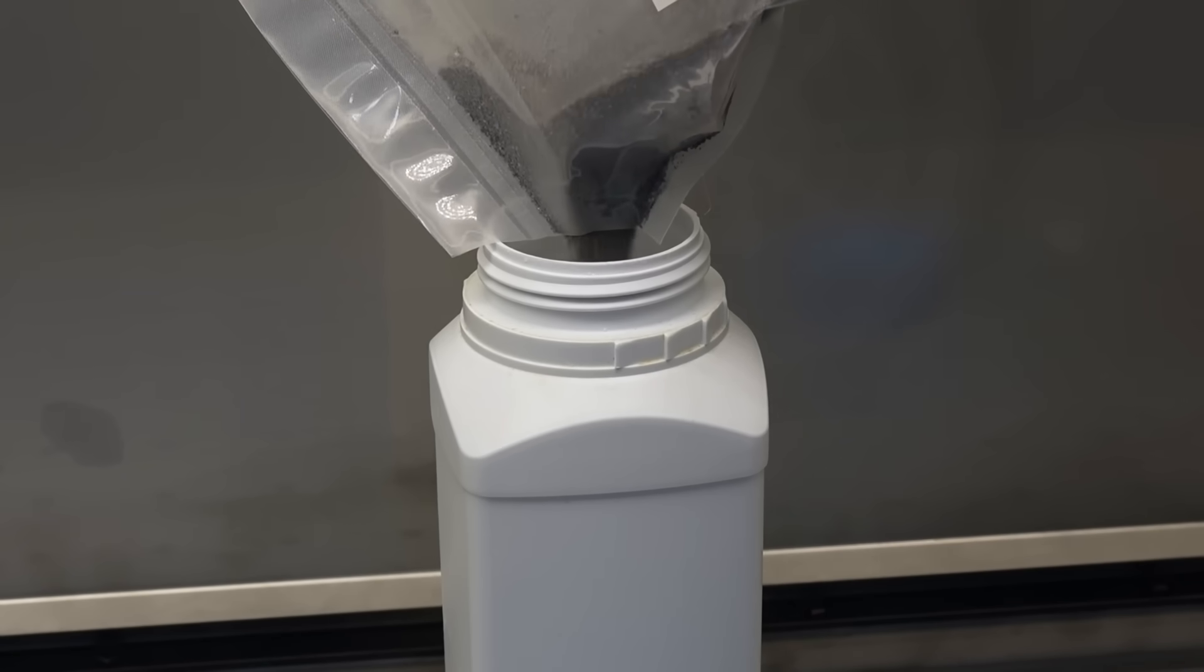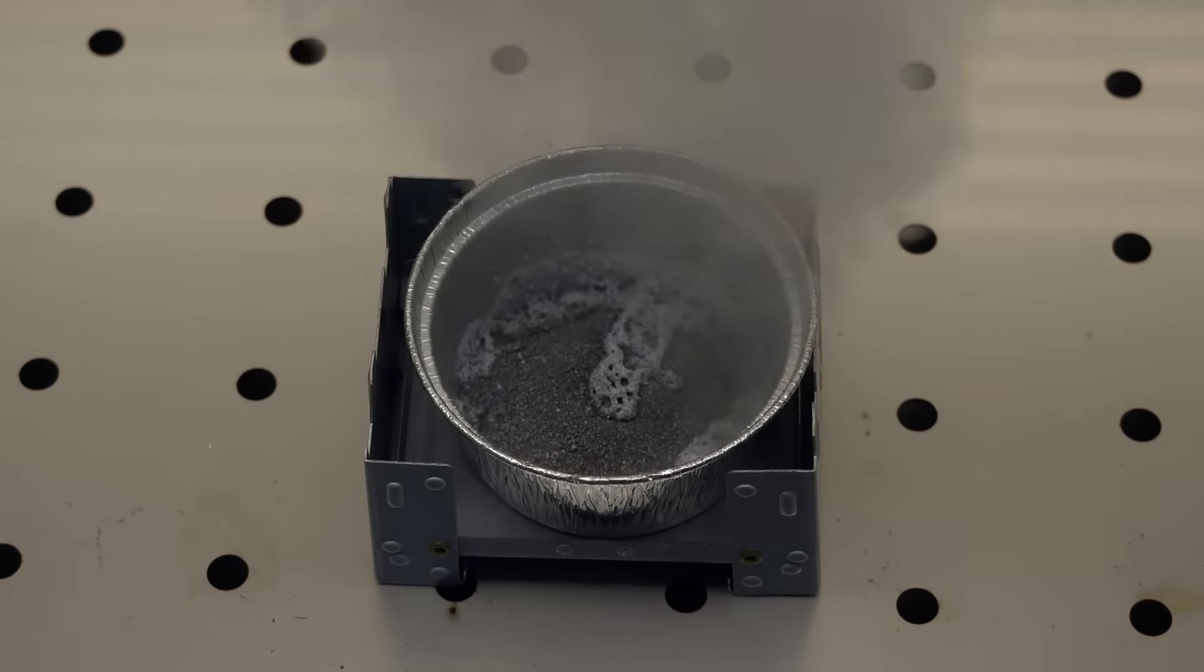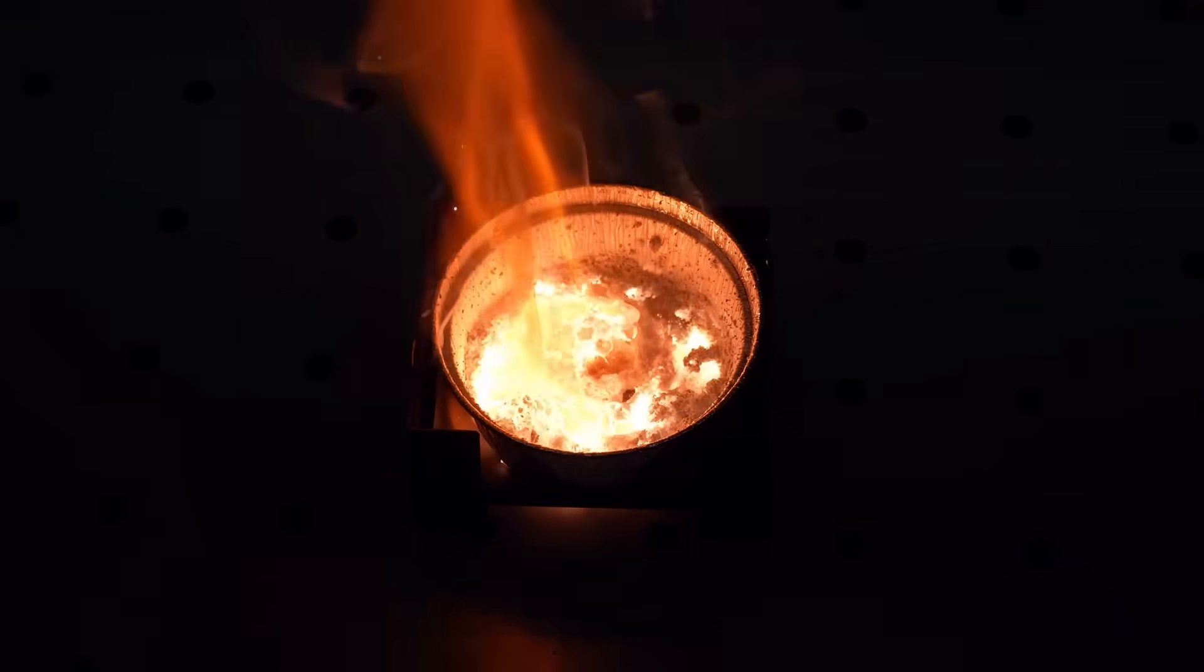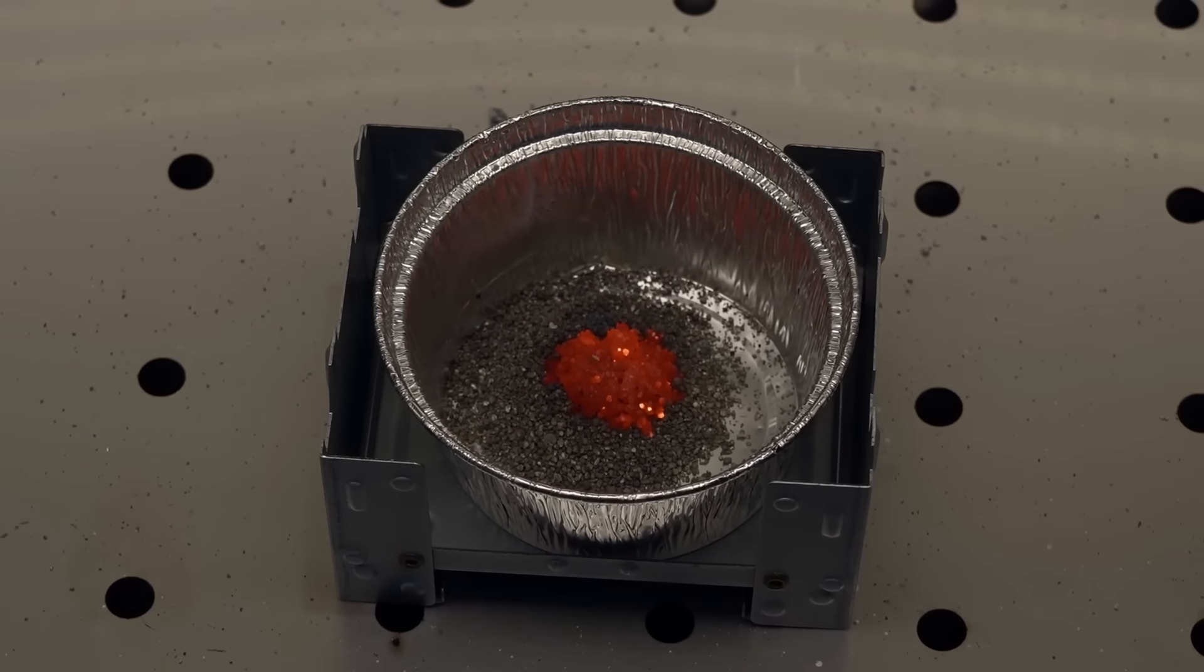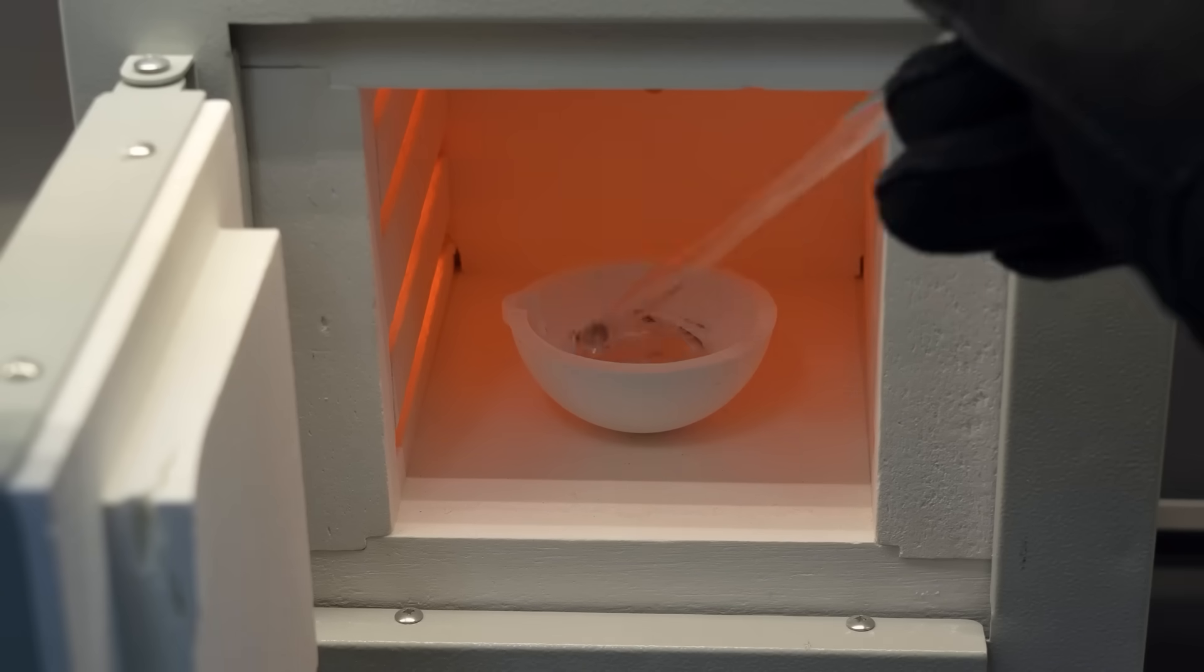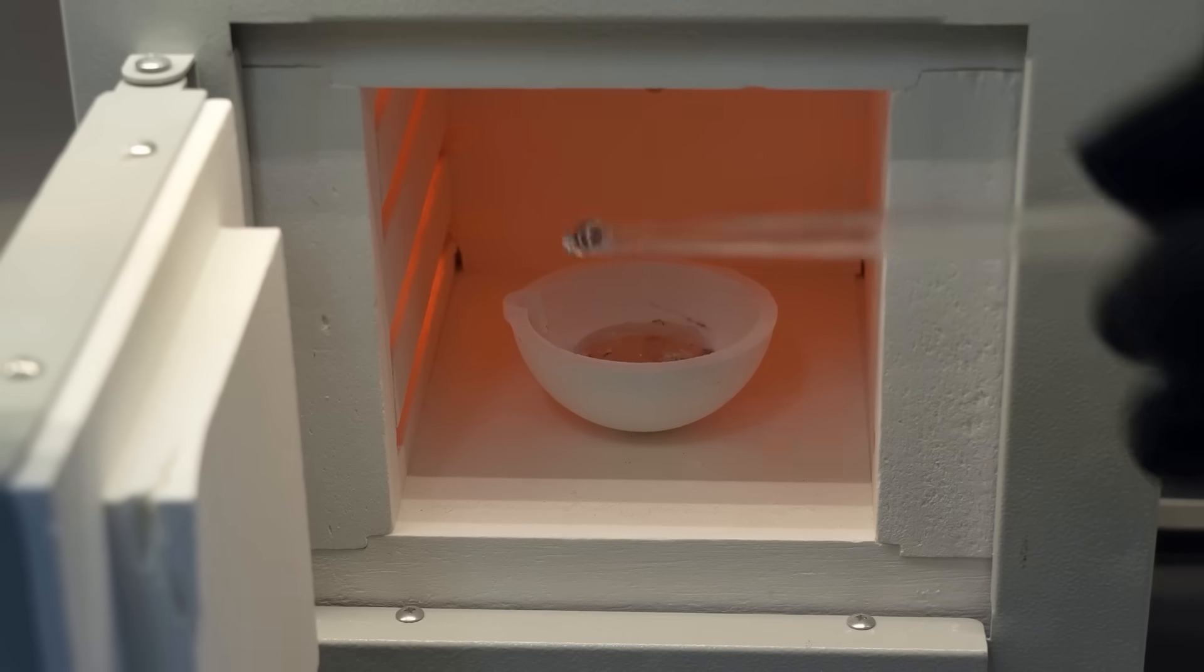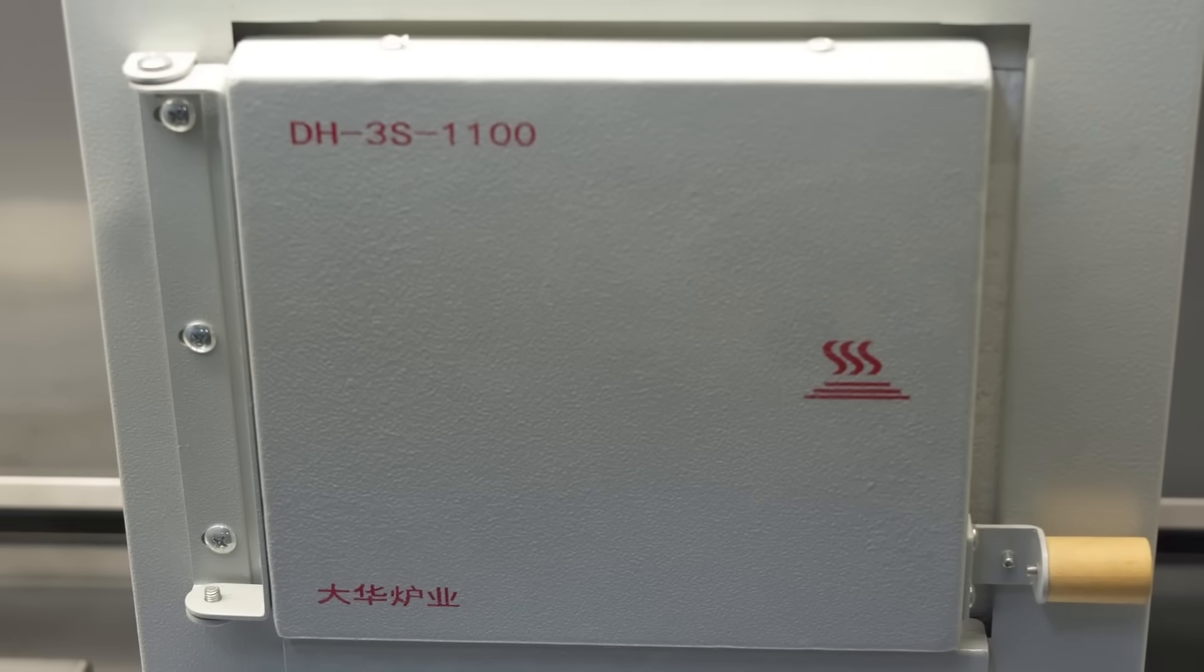In the document, I found there was a rough guide on how to obtain foam metal using various methods. One of them was the method of foaming aluminum using hydrogen. I decided to try it, specifically because it seemed the most interesting. For my experiment, I weighed out 40 grams of aluminum in a crucible, and then I added a bit of metallic calcium powder to it.